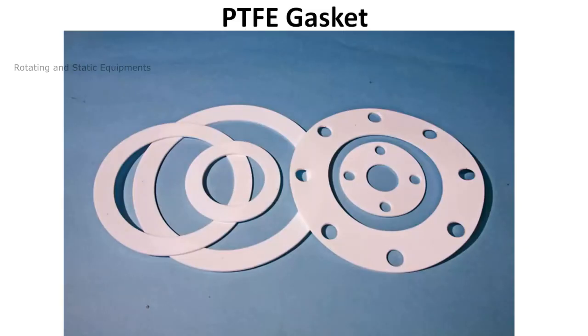Next we will go for PTFE gasket. PTFE in the sense polytetrafluoroethylene. So PTFE gasket is the most common thermoplastic gasket material. PTFE's outstanding properties include resistance to temperature extremes from cryogenic to 450 degrees Fahrenheit. PTFE gaskets are highly resistant to chemicals, solvents, caustics and acids except free fluorine and alkali metals.